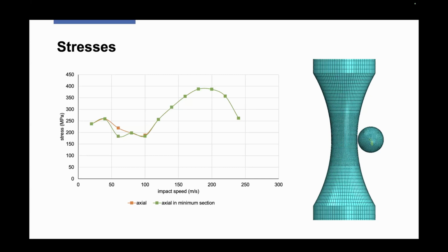First of all, the material law used, that is elastic, perfectly plastic. So we have a saturation of the stresses that the specimen can support. So when we have the elastic recovery, we have this trend. The second reason can be that it is not the case of the impact of a sphere on a plane, for example, but when the impact speed increases, the area that resists the penetration is higher. Here, this area is a little bit higher than the area in the minimum cross section. And then we have a cooperation of a larger part of the specimen due to the higher penetration. So these are at the moment the possible reasons.